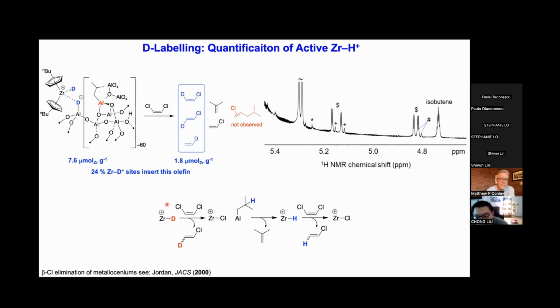So what we believe is happening here is we're taking our cationic zirconium deuteride. It's reacting with the cis-dichloroethylene, doing exactly what we want to make the deuterated vinyl chloride. Then this deactivated zirconium chloride cation, which cannot propagate polymer, is statistically close to a bunch of partially hydrolyzed aluminum alkyls on the surface. And this we know from mass balance and tracking everything going on in the reaction. So this is just a realkylation step that then releases isobutene to generate a zirconium hydride, and that generates our proteovinyl chloride. And then if this is correct, you would expect roughly a 1-to-1 ratio of these two products, which you can eyeball from the proton NMR.